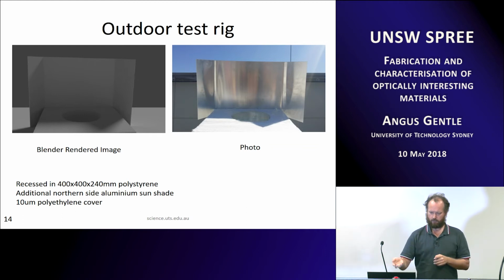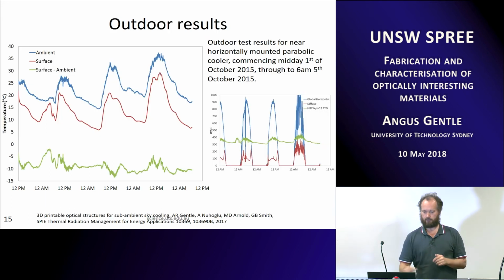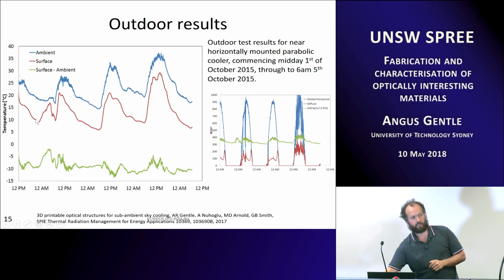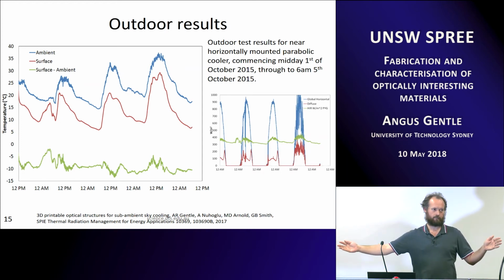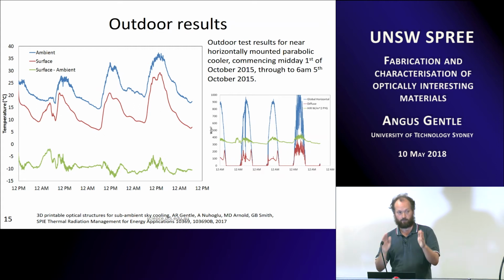And then also, a few slides back I had the one where you can measure how much sky radiation is coming down. We printed out parabolic reflectors exactly the right size that could fit over those sensors, put it on, and you see a 10-degree drop in effective sky temperature by doing that because it's blocking out the high angles. And so when you do that to a surface, you've got ambient temperature, you have 10 degrees below ambient, and this was in October. So the other stuff we did previously was in June. This is October. You've still got diffuse sunlight coming on, but we're sitting 10 degrees below ambient over multiple days continuously. And that's basically because you're blocking the high angle.